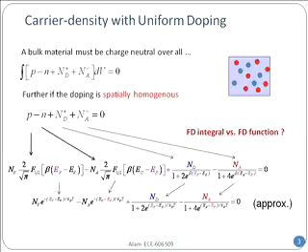And then you check the argument: is it more than 100 millielectron volts below the conduction band and 100 millielectron volts above the valence band? If it is, then I am done. If not, then I go back to the top expression because that's more accurate, and that will always apply.